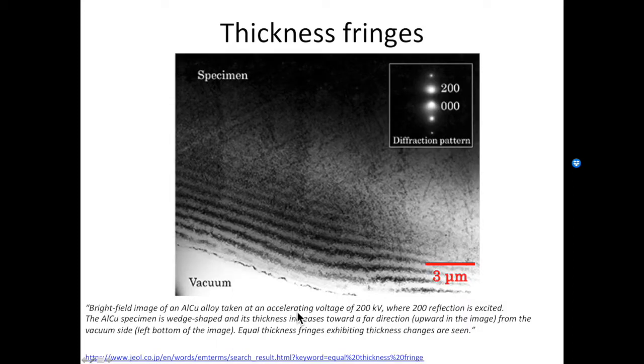Let's look at a real-life example. This image is from the JEOL website. The sample is an aluminum-copper alloy, most likely prepared by twin-jet electropolishing. The brightest part is the vacuum. As you go into the sample, you can see dark-bright, dark-bright stripes, which are the thickness fringes caused by dynamical diffraction. From the diffraction pattern you can tell it is a two-beam condition, and since the vacuum is bright, you know it is a bright-field image.